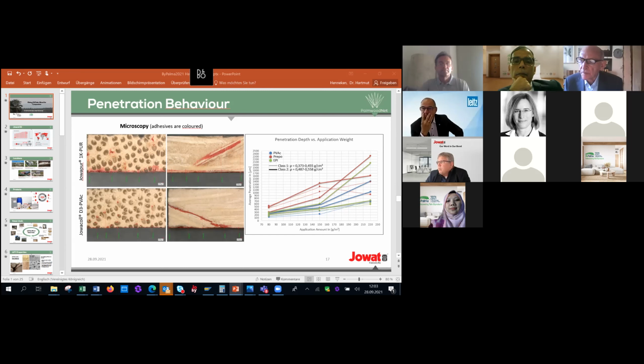We try to plot this. It's difficult to really have it quantified because it's quite a subjective impression always. But you can see for 80 grams, for 150 grams, and for 220 grams application amount, it's always the prepolymer adhesive that is penetrating deeper into the material, and then the PVAC dispersion and the EPI. But from subjective impressions, EPI is penetrating more actually also.